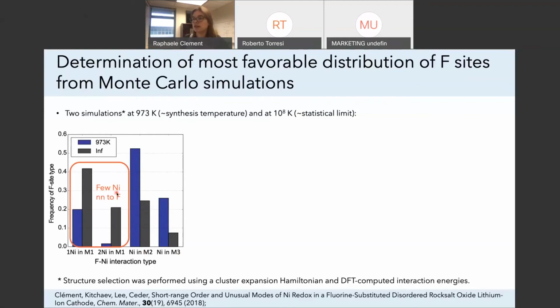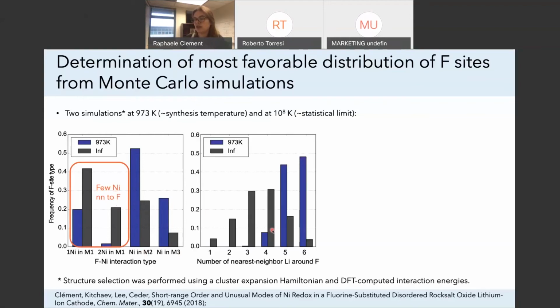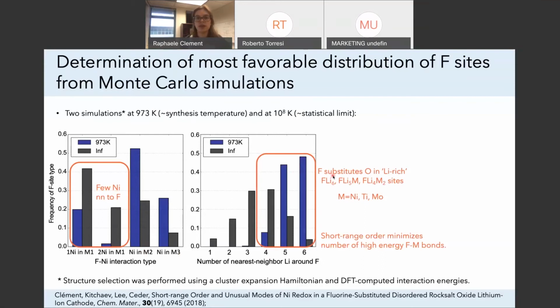And instead, if we look at the distribution of fluorine as a function of the number of nearest neighbor lithium, we find that fluorine will substitute for oxygen in these lithium-rich environments that I discussed at the beginning of this presentation. So there is clear short-range order in this material, and fluorine is integrating the structure in these lithium-rich environments, either with 6 lithium nearest neighbor, 5 lithium nearest neighbor, or 4 lithium nearest neighbor.